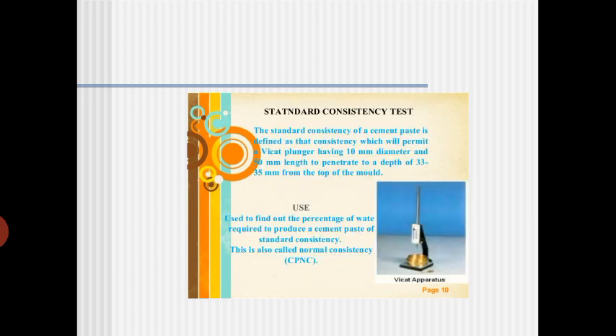So then, the standard consistency test. This standard consistency test is used for cement, and we prepare the cement paste here, and we require one plunger, and with that plunger we allow it to penetrate to 33 to 35 mm from the top of the mold. The use is to find out the percentage of water required to produce cement paste of standard consistency. Means how much quantity of water is required for standard consistency, that is the main use of it. Sometimes it also has the application of finding the water cement ratio. Based on this itself, we find out how much water cement ratio is required to get the standard consistency.